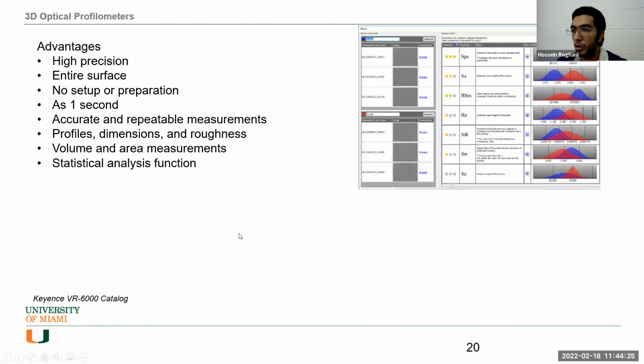But there are other equipments that hopefully we are going to use. We are trying to consult with the company to use 3D optical profilometers, which have a higher precision. It can measure the entire surface in 1 second. So you do not need to do several measurements every 10 microns. It's crazy. It can do it in 1 second. The results are accurate. You can repeat them easily, very fast. It can give you the profiles, the dimensions, the roughness, which is our main concern here, and also the volume and the area measurements.